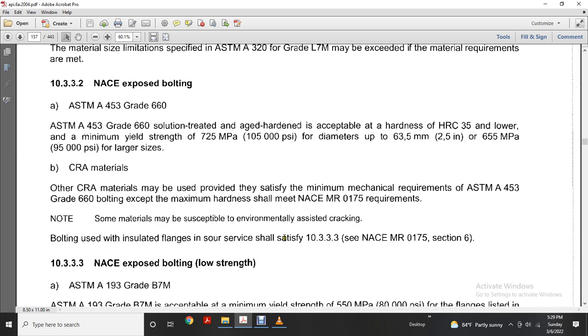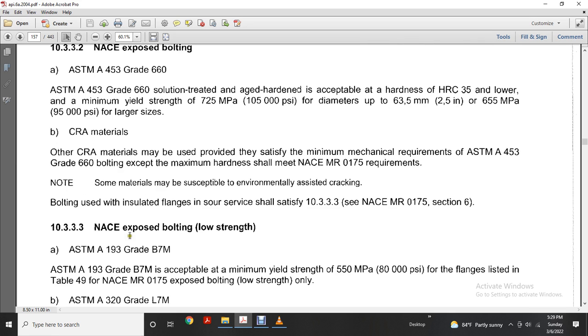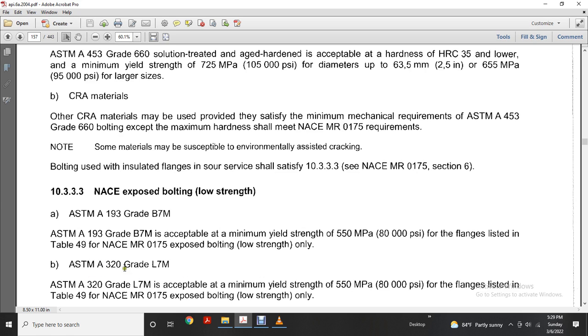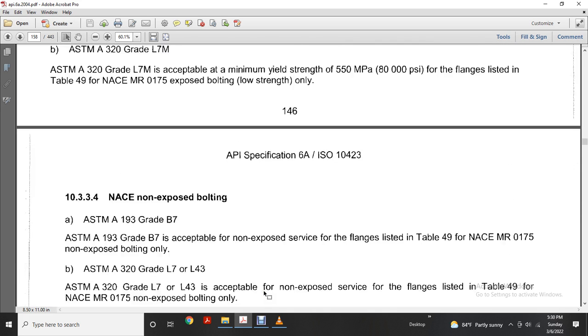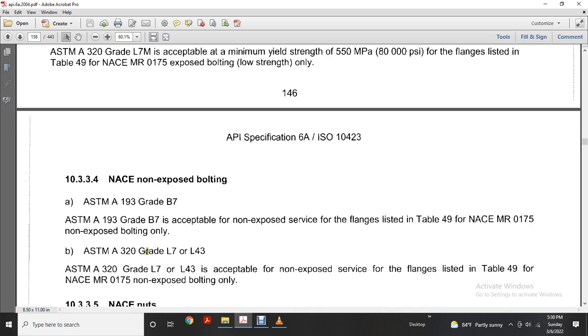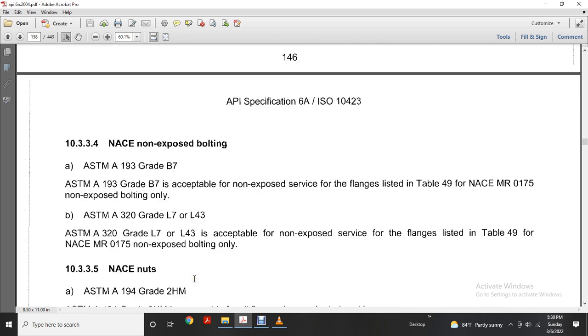Bolting used with insulated flanges in sour service shall satisfy NACE MR0175 section 6. NACE exposed bolting, low strength: ASTM A193 grade B7M is acceptable, minimum yield strength 80,000 PSI, for flanges listed in table 49, for exposed bolting low strength only. ASTM A320 grade L7M is acceptable, minimum strength of 80,000 PSI, for flanges listed in table 49, NACE MR0175 exposed bolting, low strength only. A193 grade B7 is acceptable for non-exposed surfaces of flanges in table 49, non-exposed bolting only. A320 grade L7 and L43 are acceptable for non-exposed surfaces of flanges listed in table 49, NACE MR0175 non-exposed bolting only.